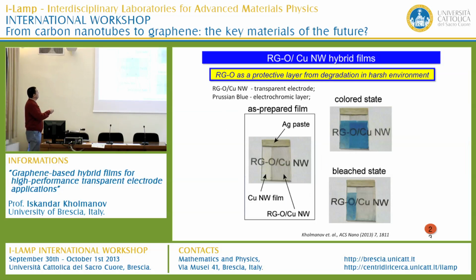So here we tried this kind of electrode. Half of the electrode is coated by the reduced graphene oxide copper nanowire film. The other half of the electrode is only pure copper nanowire film. Then we deposited Prussian blue film on top of this electrode. You see that homogeneous deposition of the Prussian blue film can be obtained.